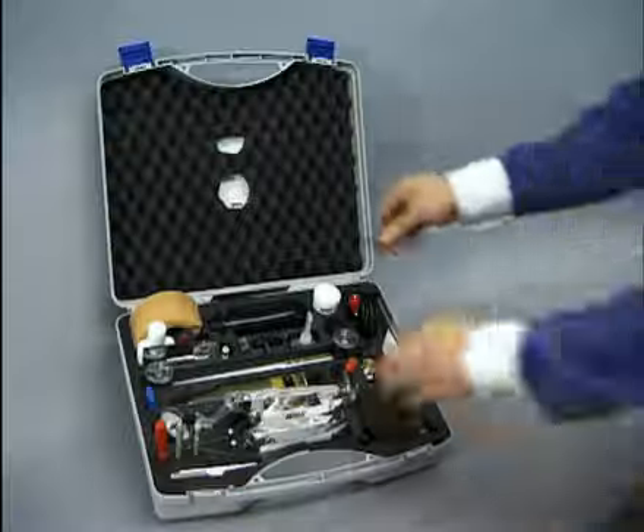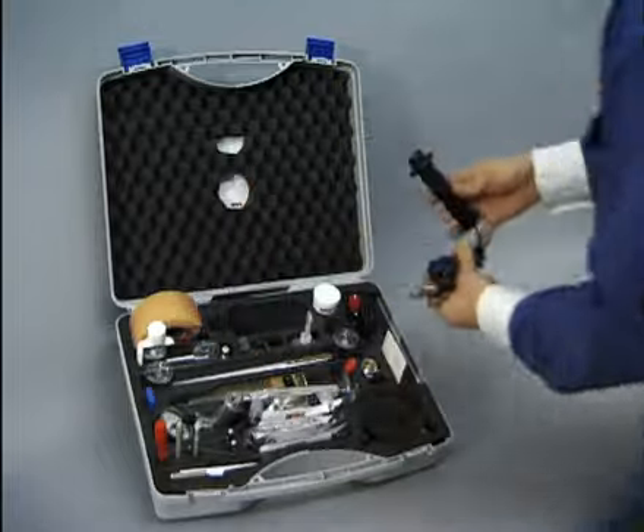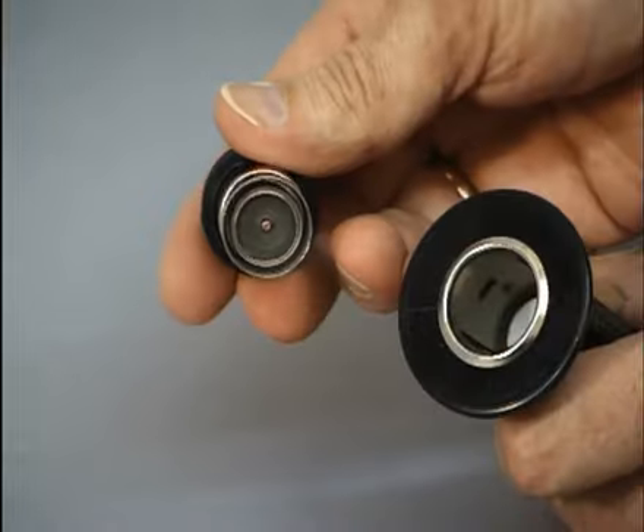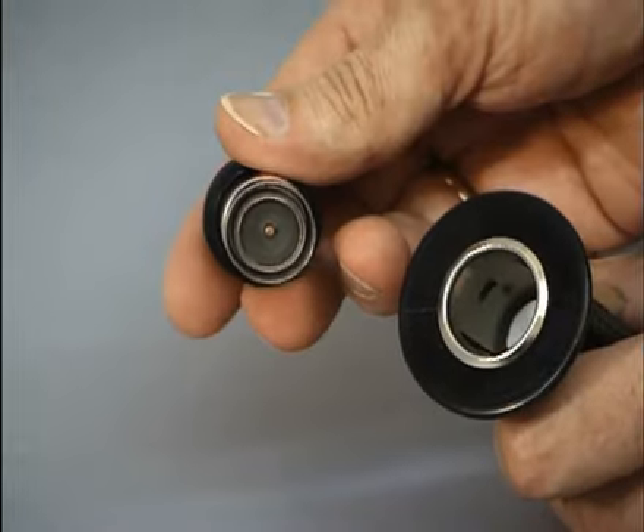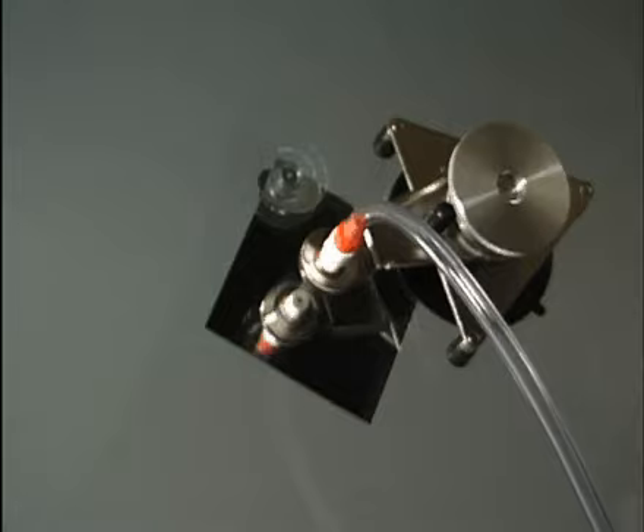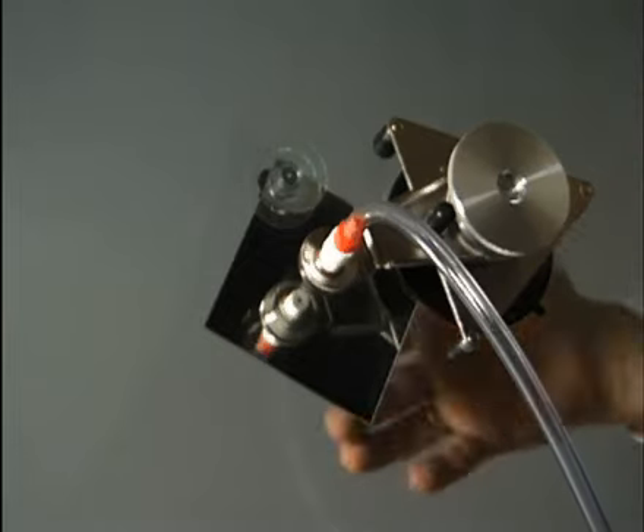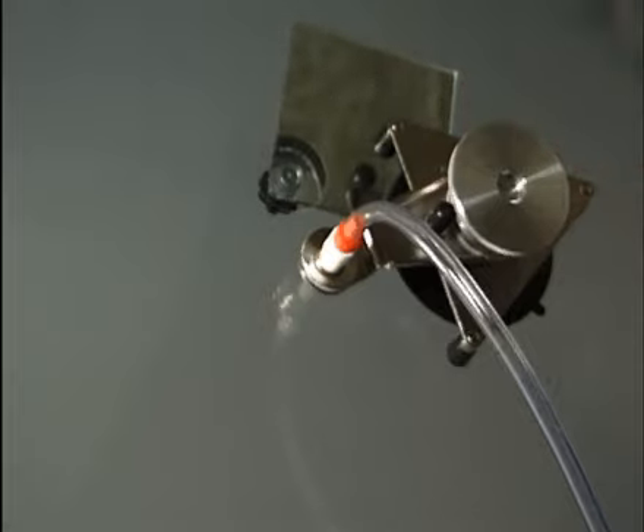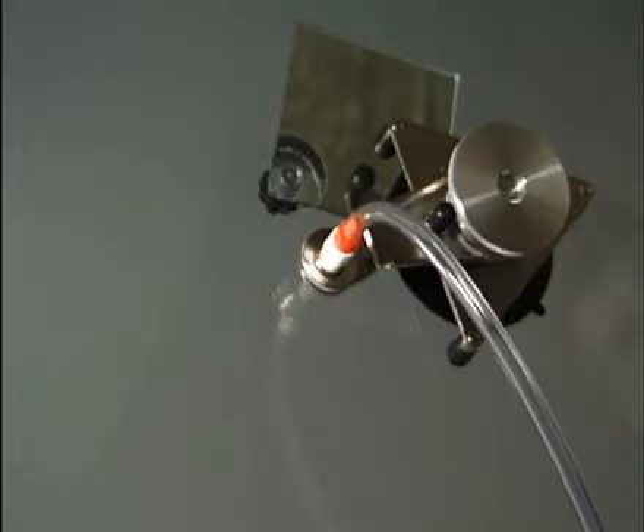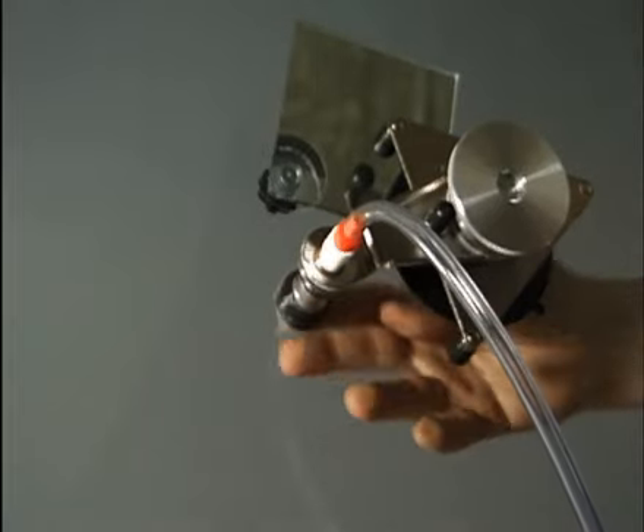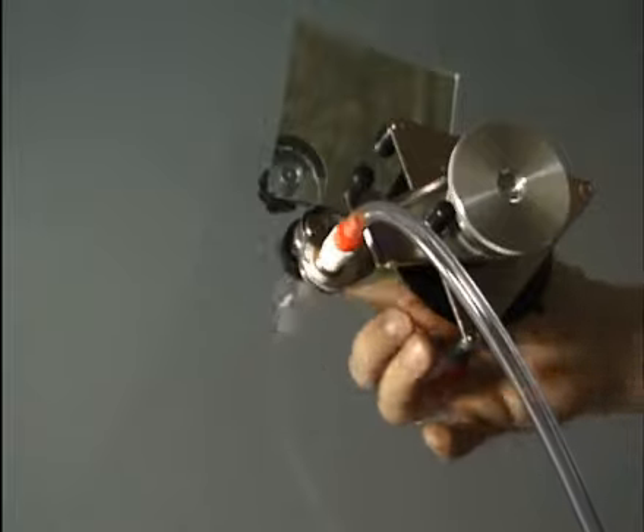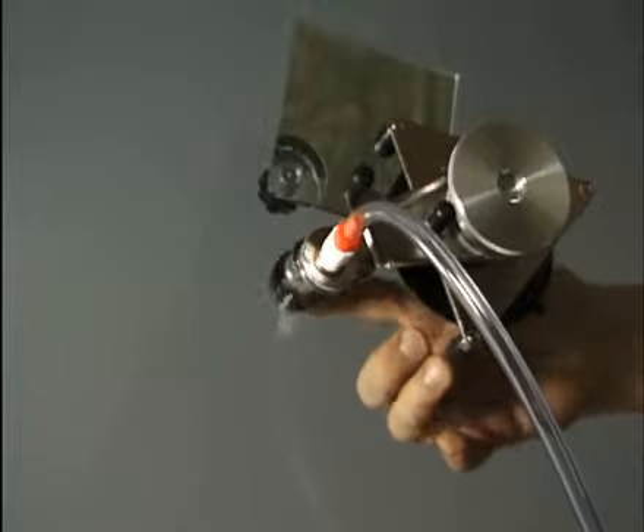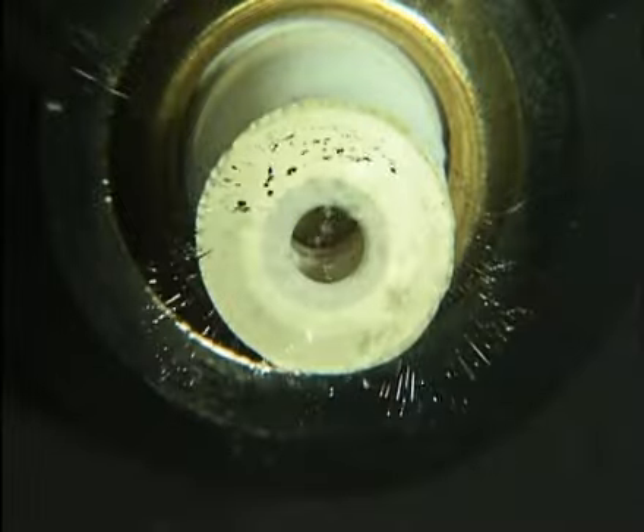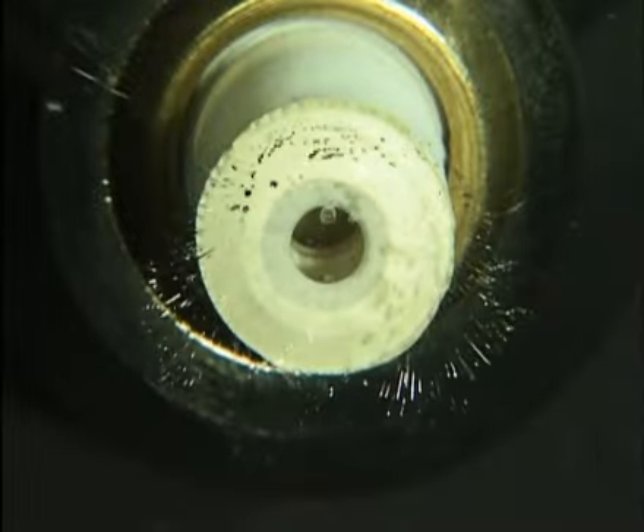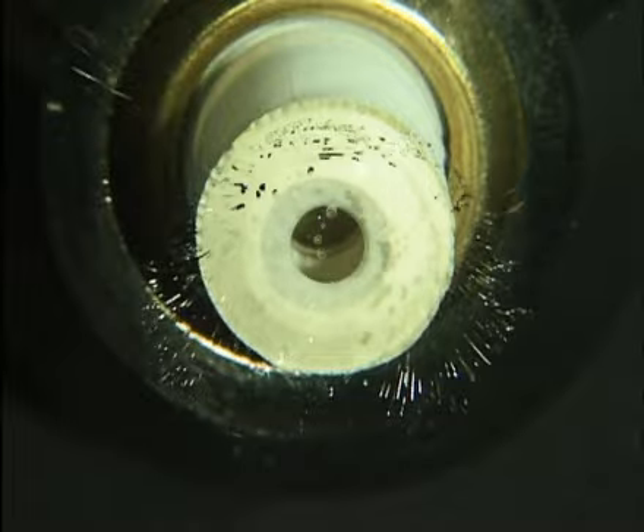By applying heat to the back of the damaged area, using a cigarette lighter no more than twice, the remaining air in the damaged area will expand and escape more easily through the resin, which is made thinner by the heat. Furthermore, the resin, made thinner by heat application, will flow more easily into the damage. After applying heat, maintain the vacuum for some minutes.